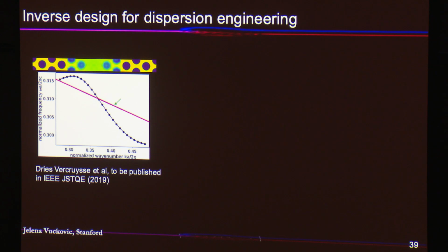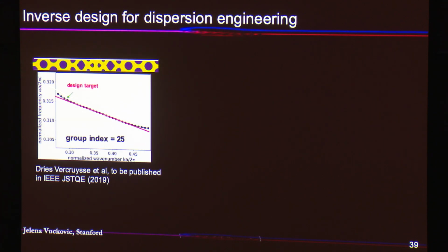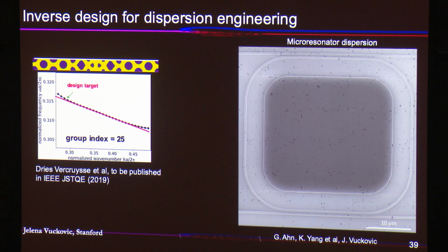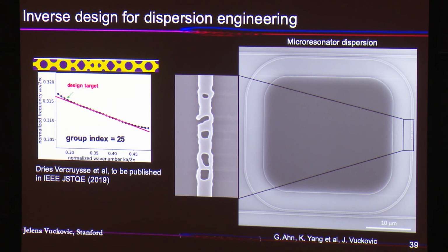And we actually can do that with our inverse design, because we can literally draw the desired dispersion. And manually, you can never really reach that, even in photonic crystals. But with our techniques, you can optimize it to reach the design target for whatever group index you would like to have and whatever is physically possible, and of course with fabrication constraints. And we can also use that dispersion engineering to engineer microresonator dispersion, and if you're building something like a frequency comb, you can actually achieve the flat spectrum. We insert an element which has desired phase shift as a function of frequency, and that impacts the frequency comb spectrum, so you can actually make better frequency combs in principle. And that's kind of the idea of dispersion engineering.